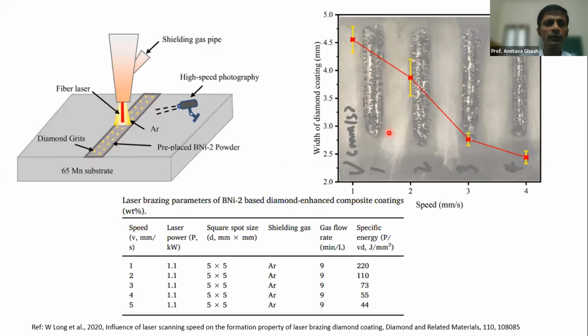So here again, as is quite understandable with common logic, the lower the speed, the longer the laser will be exposed to the diamond. And the major disadvantage of laser technology in this particular approach is that when we approach the interface, it is through the diamond, of course. So it is not that just the root can be exposed for the heating. Of course, you can have a temperature gradient, but that is very, very difficult.